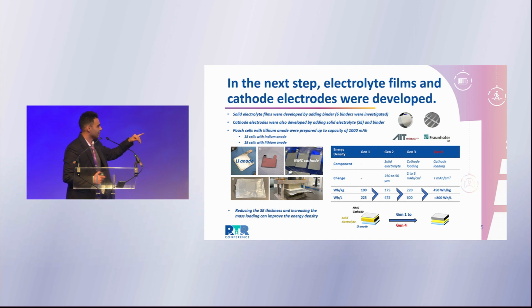So here, I have shown this in the animation at the bottom. For us, it was the low cathode loading and the very high solid electrolyte thickness that resulted in this low energy density. However, in the next generations, we can step by step tune this and reach the final energy density that's required in this project.